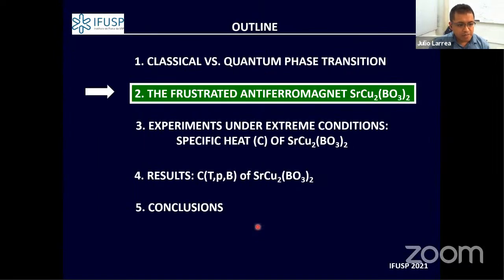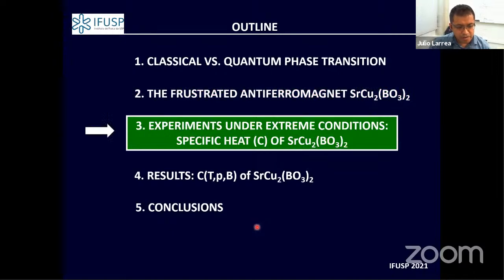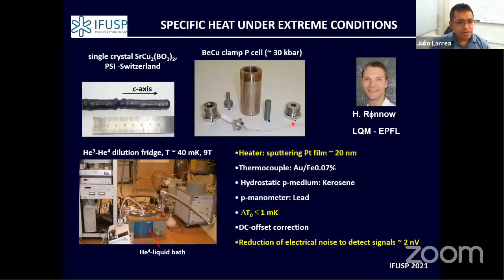This is where our experiment of specific heat under extreme conditions in this system becomes suitable. Here I have shown a simple view of how the crystals are grown. In principle, a big single crystal was provided by collaborators at the Paul Scherrer Institute. In this case, the crystal is grown along the c-axis. For our experiment it is grown in a big piece because people are also doing neutron scattering experiments. But for our experiment under pressure, we need only a few milligrams of this sample. We cut it into a slice and can put it in this non-magnetic pressure cell, reaching pressures up to 30 kilobar.